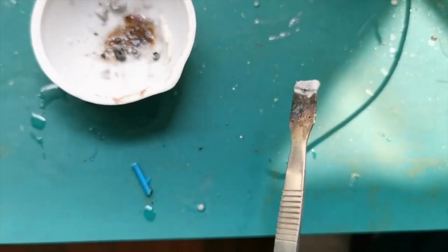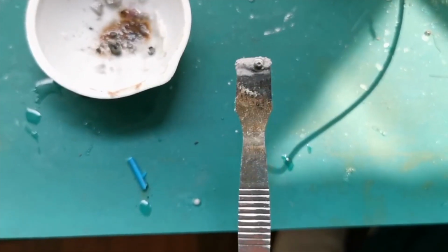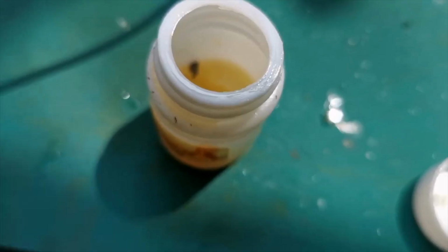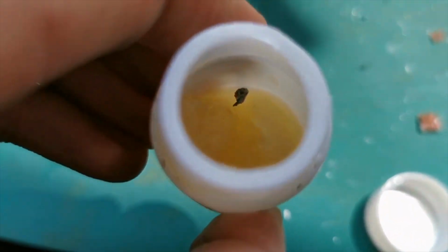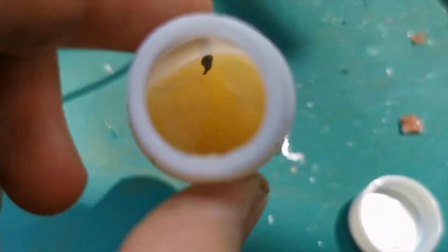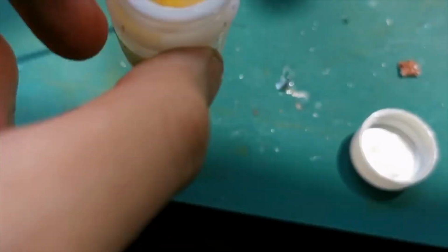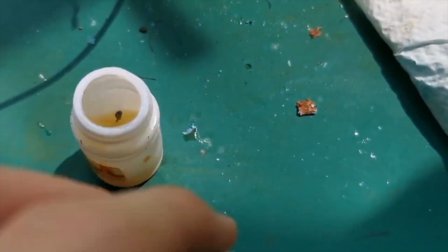I carefully removed just a bead and left the rest of the salt behind, and finally put the bead into a vial of Vaseline. This is our yield of lithium metal. It's just a tiny bit, but it was very shiny, and it even floated on the Vaseline, which tells me